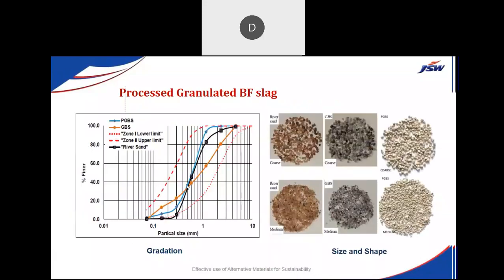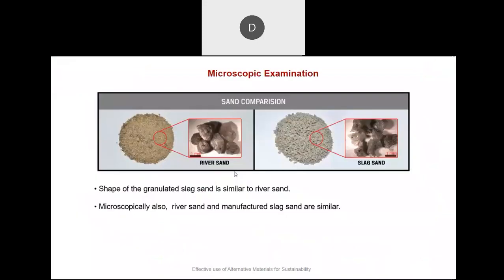It meets the zone 2 requirement, the blue curve. This is the processed slag sand. You can see the patterns we have taken out. It looks similar to river sand.